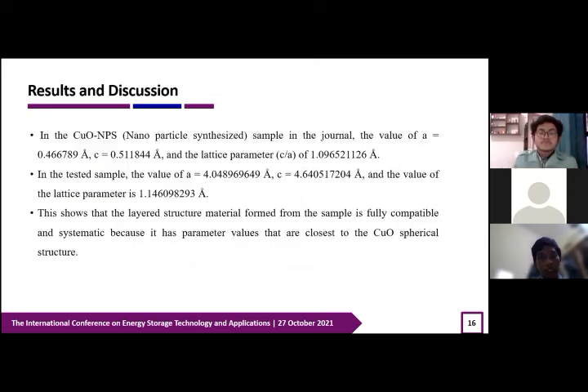the test value obtained: a equals 4.048969649 Angstrom and c equals 4.640517204 Angstrom, and the value of the lattice parameter is 1.146098293 Angstrom. This shows that the layer structure material formed from the sample is fully compatible and systematic because it has parameter values that are closest to the copper oxide spherical structure.